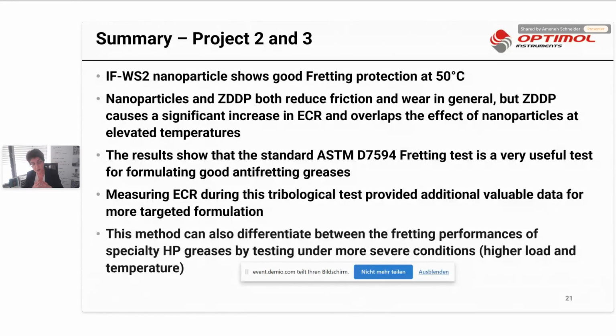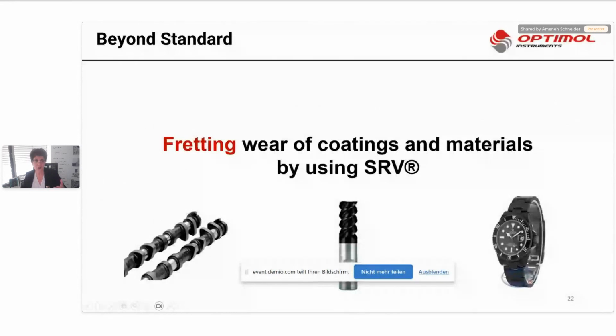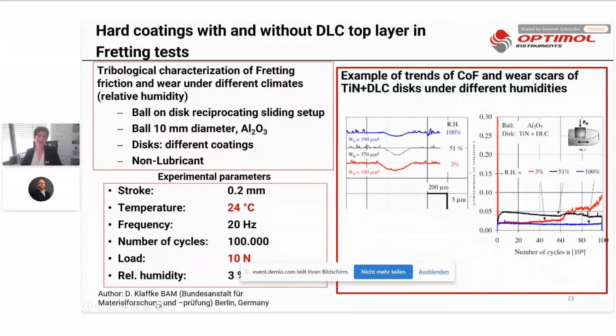And you have seen in project number 3 that you can use this fretting test even for more severe conditions, like much higher load and temperature than is written in the standard method. One example beyond this standard method is the fretting wear of coatings and materials, which can also be studied using SRV. One very nice example I brought for you is from the work of Dr. Klaffke from BAM. His topic is hard coating with and without a DLC top layer in fretting tests. He studied the tribological characteristics of fretting wear and fretting friction at different climates, at different humidity, using ball and disc.